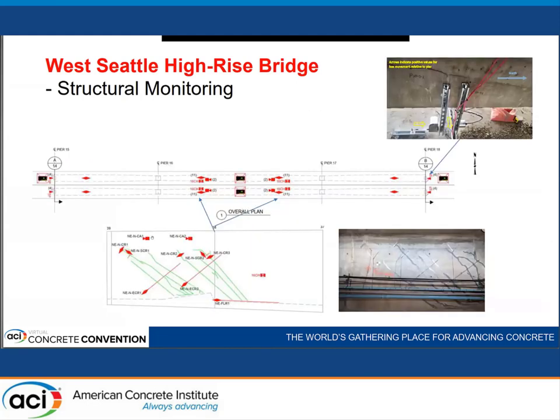For example, in each of the quadrants of the bridge where this cracking was forming near the anchorage blisters, you would see these diagonal crack formations. So we would gauge individual cracks across the crack as well as groups of cracks with an extended gauge to get cumulative behavior. And then what we call slip gauges were oriented transverse to the crack to see whether there was any movement on each side of the crack, in a sort of shear behavior across that crack.